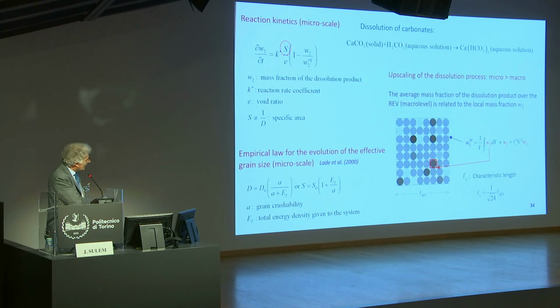So we have this simple relationship for the evolution of the specific surface with one material parameter, which is the grain crushability. Now, what we write here at the grain scale, we have to upscale it at the scale of the elementary volume. So this is this upscaling from micro to macro. And this is done by averaging the mass fraction of the dissolution product over the macro element here. So this is the averaging. And we do just to the second order Taylor development. So this naturally introduces the second gradient here, and with some material length, which is related to the size of the REV. So you see the characteristic size of the problem is actually the dominant wavelength of the heterogeneity of here the dissolution process.